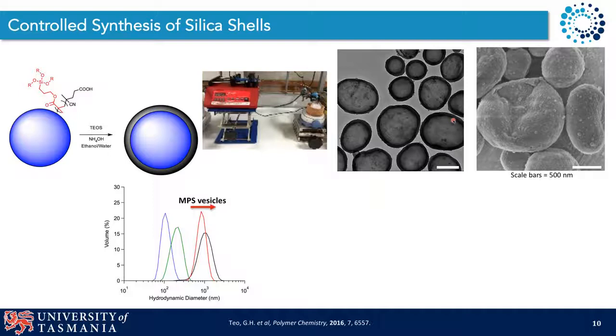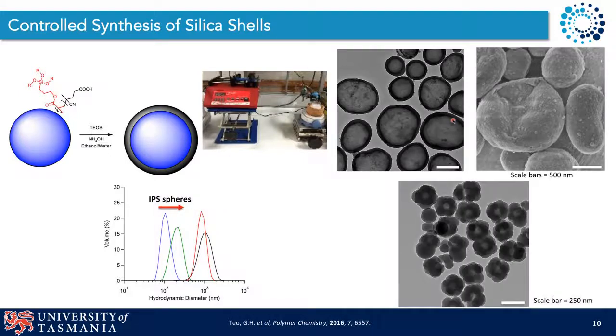When we used the isopropyl functional nanoparticles, we do get a controlled growth, but our morphologies are no longer smooth. They are essentially lumpy or raspberry in nature, and that was attributed to the difference in the hydrolysis and condensation rates of the methyl group, the isopropyl groups on the surface, and the TEOS precursor.